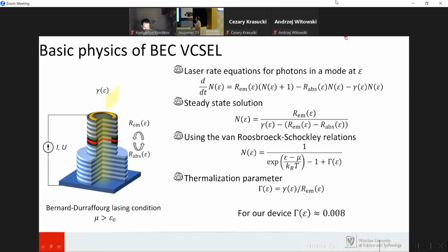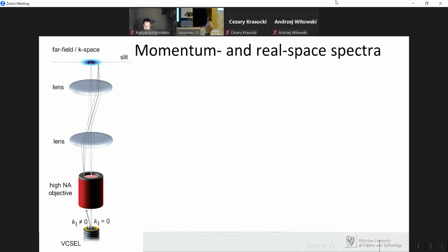And most importantly, every VCSEL will go to lasing if we drive it too hard. So this is the regular standard condition when we have gain in the system, when the chemical potential in the bands is above the energy of the cavity mode. We do the far field, so also dispersion measurements, as shown before.